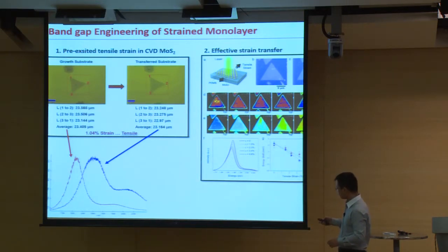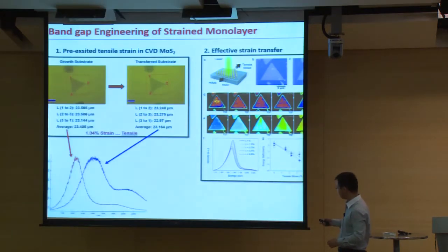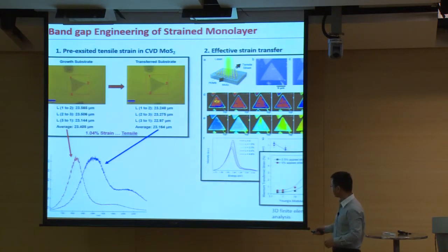So what's the problem? By finite element calculation, what we can see is the Young's modulus of the substrate plays a very important role. So if you can make the Young's modulus more than 1 gigapascal, most of the strain can be transferred to the molybdenum sulfide in the substrate. So Young's modulus is really important for this kind of strain experiment.